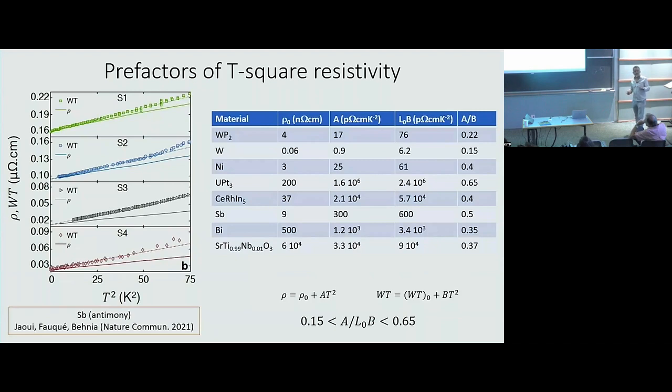So experimentally, there is a very simple recipe. You put a magnetic field, and you assume that phonons don't care about magnetic field, or if they care, it is about 1%. If you look at antimony, for example, as soon as you put a magnetic field of 1 Tesla, your electrical resistivity blows up by 6 orders of magnitude. So what remains is your phonon thermal conductivity. So you apply a magnetic field, look at the temperature where nothing is changing, and you say below that it's all electronic? No. So I try.